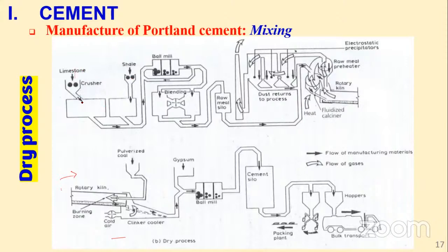So limestone is crushed. The limestone now, which brings the calcium, and the shale or the clay, which brings the alumina, the silica, the iron, they are mixed together. They are crushed, then the powder will be mixed together. Of course, they are reduced to small form, not powder form. That's why we take them to the ball mill, so that here they will be ground to very fine powder. And then they are taken to the blending to end up having raw mix. Okay. Now that material will be fed.